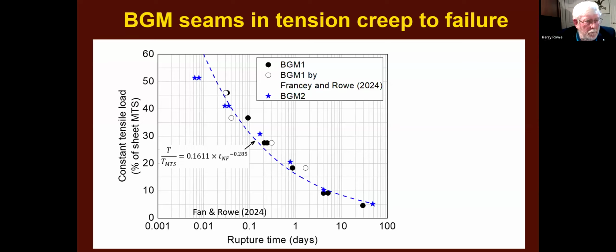And all of these welds were within 10% of the sheet strength. Many of them were as good as the sheet strength in a short-term test. And so they were good welds that we started with. We did do some tests on not such good welds, and it really didn't make much difference. So here you see the data for 2 different BGMs from 2 different manufacturers correlating very well. And you see that if we go to 30% of the strength of the material, it failed in 0.1 of a day.